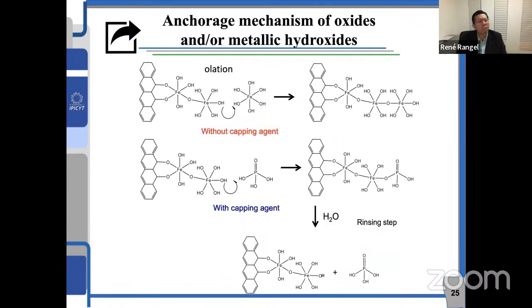And this is the mechanism we have published many times. If we don't use a capping agent, the clusters of the metal oxides can increase, and then we end up with quite a big particle. But if we use a capping agent such as phosphorus, in this case, we manage to block the growing of the metal oxide.